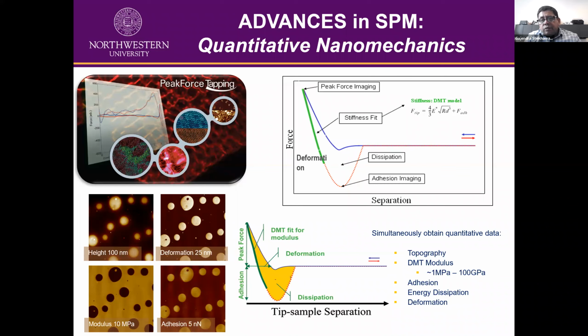So likewise, the lateral forces from a hard sample can cause the end of a tip to fracture and break off. So normal forces can also cause damage to both tip and sample. Even if there is not enough normal force to damage the sample, there can still be enough to deform the sample, increasing the contact area. So in this regard, in peak force tapping, the probe and sample are